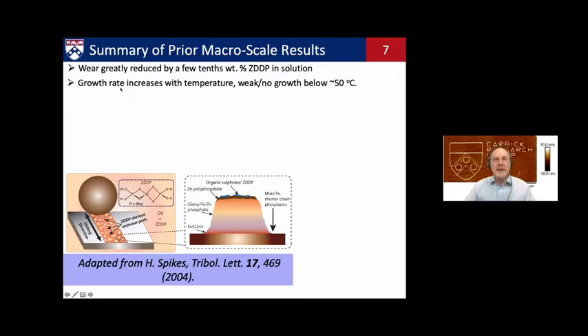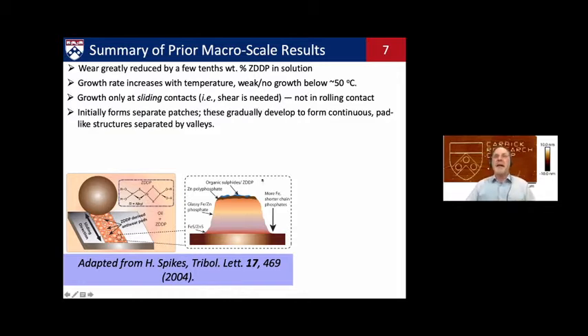The growth rate increases with temperature, so there is definitely thermal activation of the chemical processes occurring, such that below about 50 C, you don't see much growth of useful films. You only see growth where there's sliding. You need shear, not just normal pressure, not just rolling contact. And the films form these patchy-like structures.